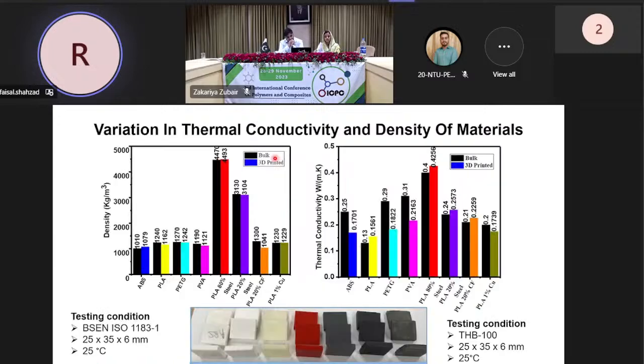Then we measured the thermal conductivity and density of the materials, because in a battery thermal management system these two things are very important. First is the thermal conductivity, which should be good, and the second is the density. So we are trying to find a material with low density and high thermal conductivity. Most metal materials have really good conductivity, but because of their weight, for example copper has a very high thermal conductivity, we can't use it in battery thermal management systems with different filaments, because it will increase the weight of the battery pack.